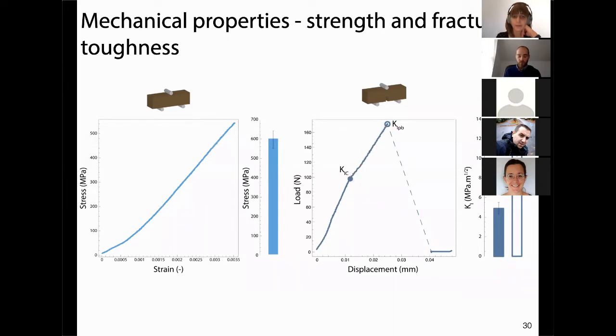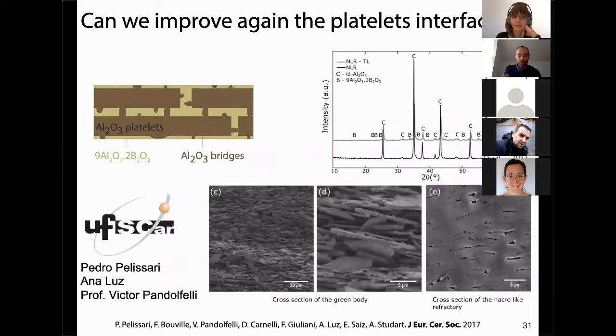And we try then to see if the interface again has an influence on the mechanical properties. So we know the amount of interface is important, but we wanted to check if just the composition, so the strength of the interface, is also important.